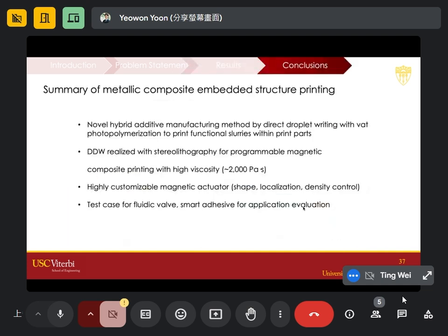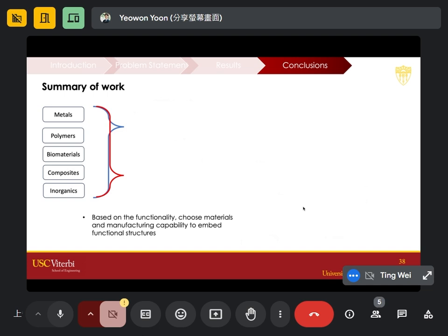So this secondary study is on hybrid additive manufacturing, incorporating direct droplet writing with photopolymerization to insert a magnetic soft powder inside a 3D printed structure. Direct writing is realized with stereolithography, where we can print extremely high viscosity slurry up to 2,000 Pascal-seconds. We have a highly customizable space for the magnetic actuator design, where we can control the shape, location, and the density. So we're able to pull off some test studies with the fluidic valve and the smart adhesive. That kind of sums up my talk and my work here.